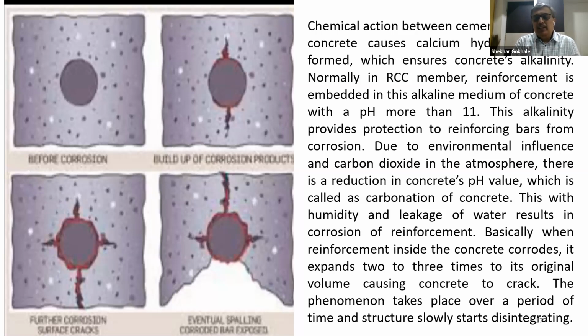So buildings constructed between 1970 to 1980 and 1980 to 1985 have more problems because there was a shortage of cement at that time, and M15 grade concrete was used. At that time Tor steel was used, and the corrosion resistance of Tor steel was not as good as present-day steel, which is Fe 500 or Fe 550 grade. So all these factors are contributing to the distressed or dilapidated condition of the buildings constructed between 1970 to 1985. These buildings are generally in the range of 30 to 45 years, and they are giving problems.